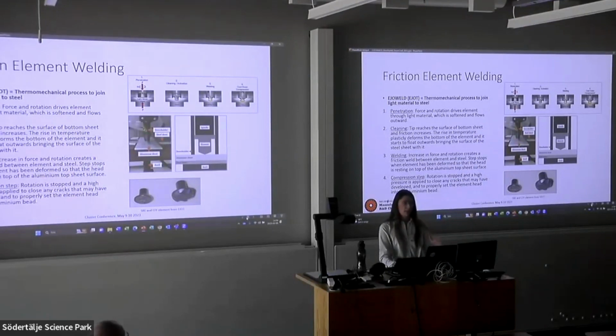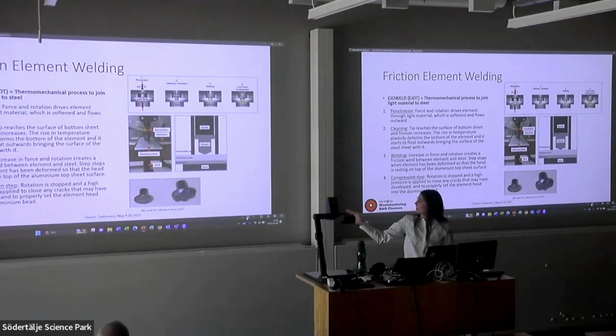At this step, a friction weld is created. So you do not mix the material. They're not traditional melted joints as such. It's a friction weld. And then at the very last step, you stop the rotation and you increase the force. This is a compression step to help lock everything in place. And here you can see 2 different elements. You have the bigger CFF element and the smaller SRE element. And they work basically the same.